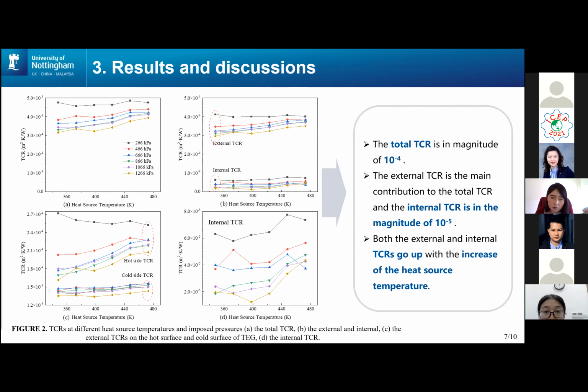The TCRs at various heat source temperatures under different load pressure are given in these charts. The first chart on the upper left illustrates the total TCR. It can be seen that the total TCR is in magnitude of 10 minus 4. The second chart on the upper right describes the variations of external TCRs and the internal TCRs, from which we can see that the external TCR is the main contribution to the total TCR, and the internal TCR is in the magnitude of 10 minus 5.